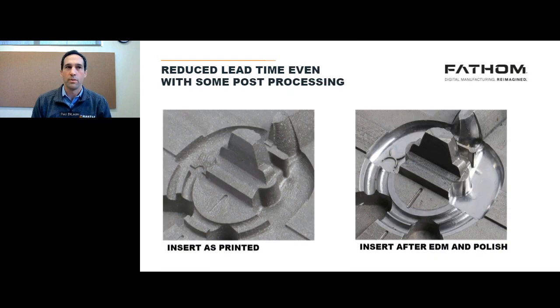So I'm showing a close-up view here. There are some features here that were thinner than what Mantle can print. Typically, we can print about 1 millimeter wall thickness. But you can see some of these ribs are less than that, and there are some features that are less than that. And so what was important to them is that they could still do the EDM operations on the Mantle printed component and do the polishing operations and have all that be seamless.